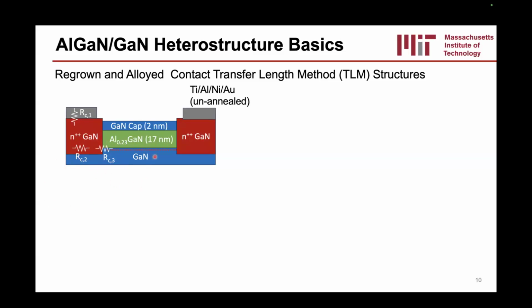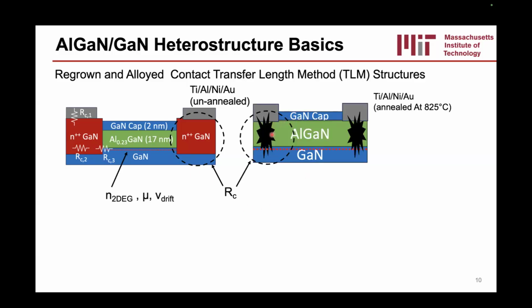Most of the properties we care about are associated with this 2D electron gas. If you ask a device person, there's 4 or 5 parameters that are really important. And most people, if you tell them these parameters, they'll know if your transistor will be good or bad. Some of them include the 2D electron gas density, how many electrons you have in there, the mobility, the low field transport, the drift velocity, specifically in the higher field transport region, as well as the contact resistance associated with the metal contact to this 2D electron gas channel. Additionally, you can have regrown contacts here, which have relatively better performance, or a little bit more standard is alloy contacts, where you deposit your metal, in this case titanium aluminum gold, and then you alloy it so that you can make ohmic contact to your 2D electron gas.